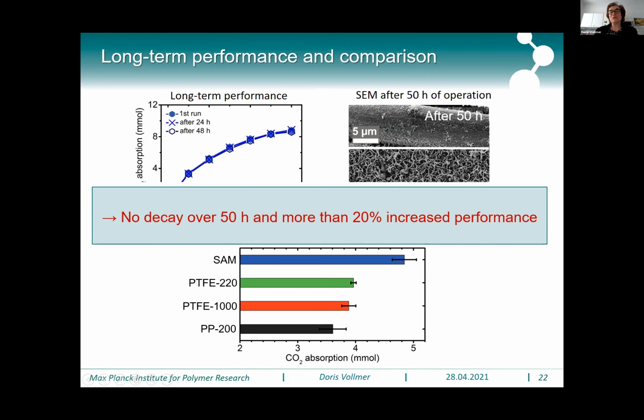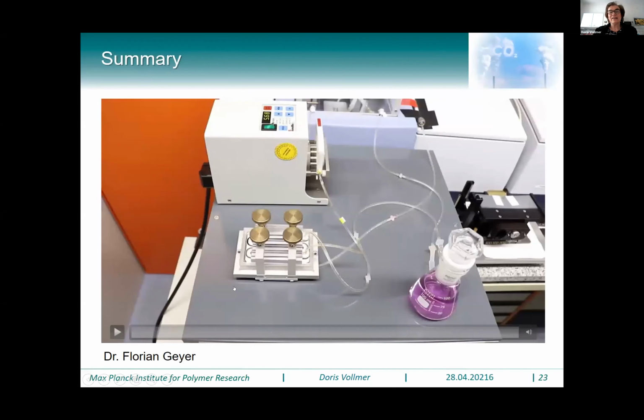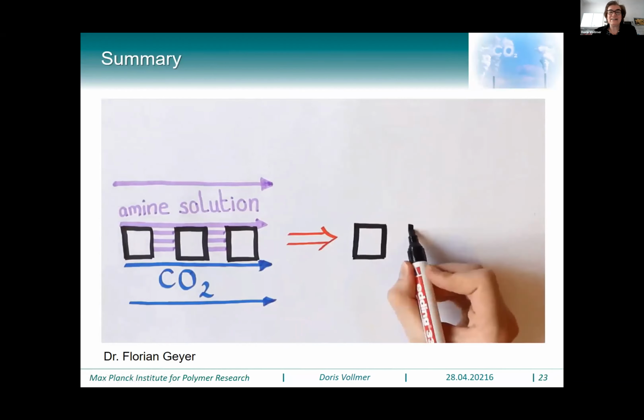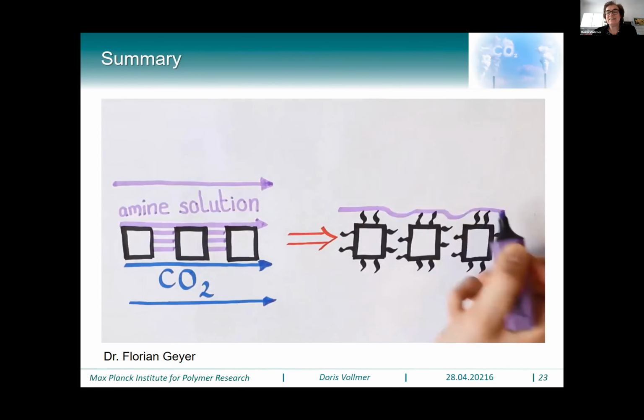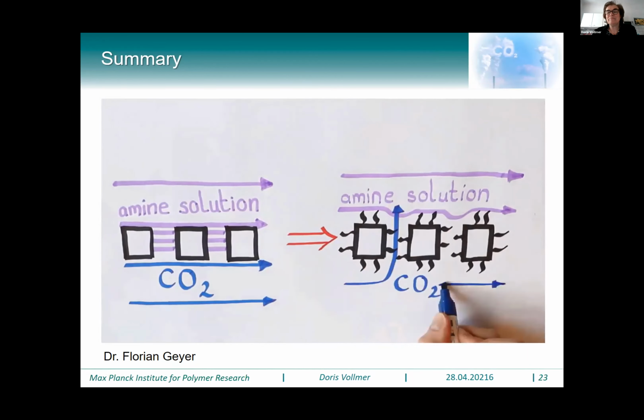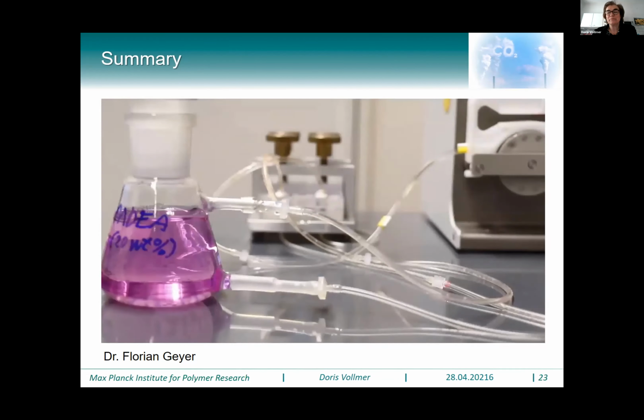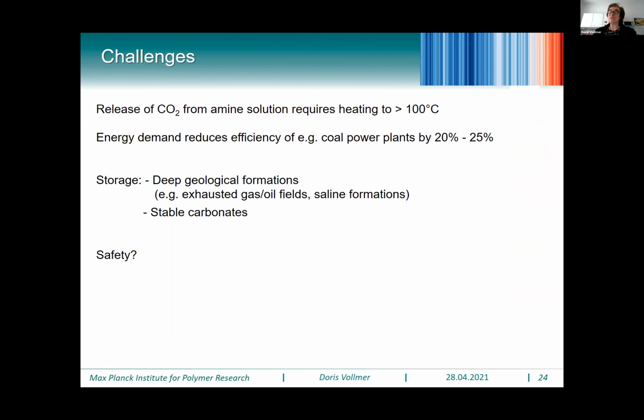With that, I'd like to summarize. To prevent wetting of the pores, we developed membranes with super liquid repellent properties. Thus, significant performance increases can be achieved to make carbon dioxide capture more efficient. I was first very happy when I saw that we had a significant increase of carbon dioxide uptake. However, then we realized that this is actually not the most important step in the problem.